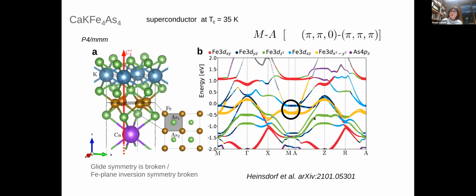So first of all, the materials I'm talking about are, for instance, calcium potassium iron 4 arsenic 4. So these materials have the same structure as the 122 materials, but what we have in this case is that there is an alternation of cations, so calcium, potassium, calcium, potassium, what makes this a structure where the unit cell has 2 iron planes per unit cell. And because of these different cations, we are breaking explicitly the glide symmetry that is otherwise present in all iron-based superconductors. So what we have in this material is there is no glide symmetry. And because there is no glide symmetry, there is also no iron plane inversion symmetry.